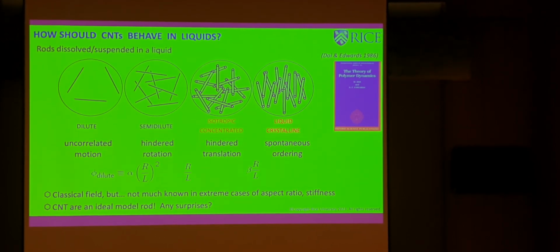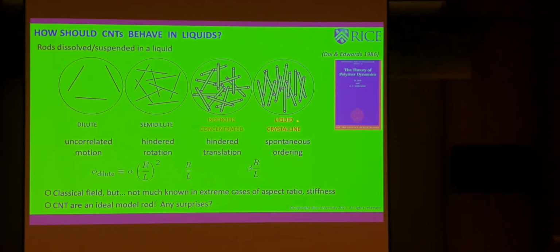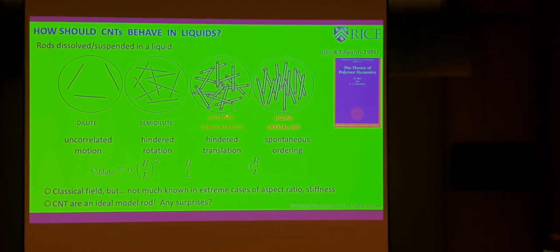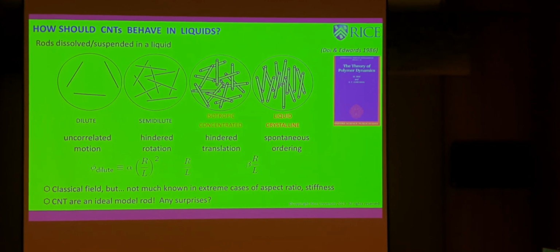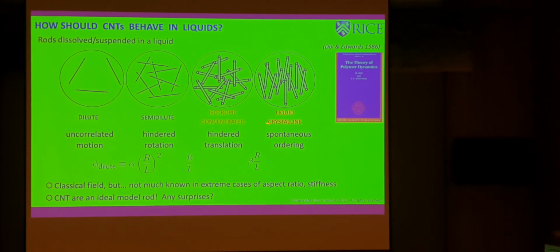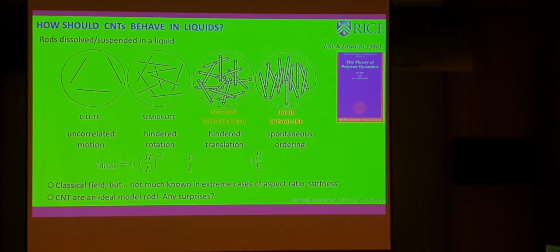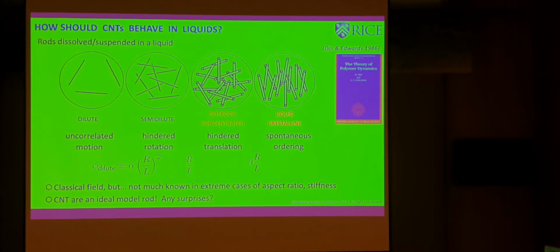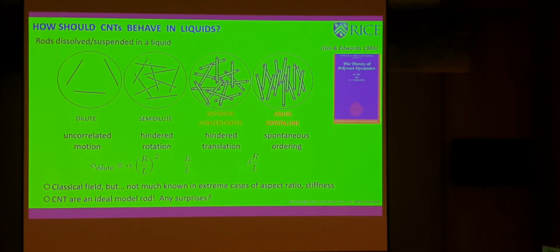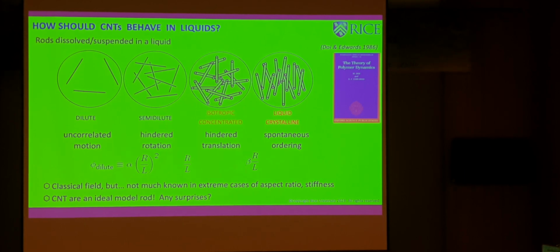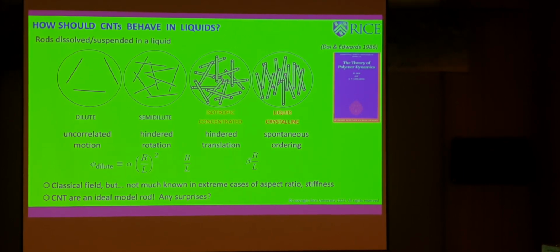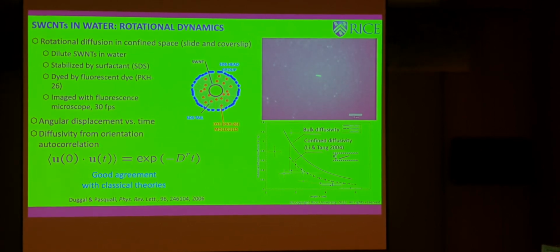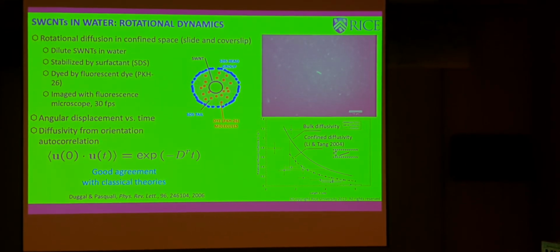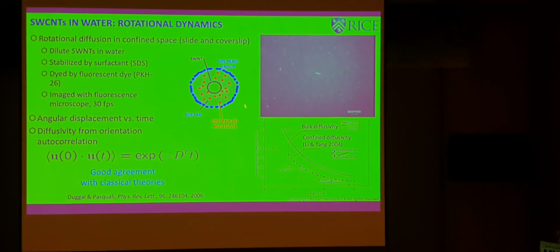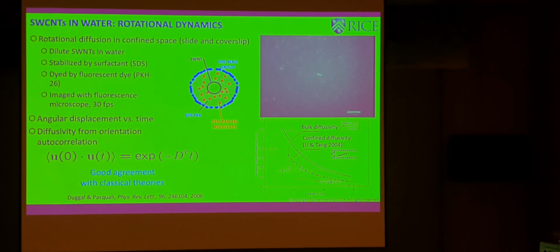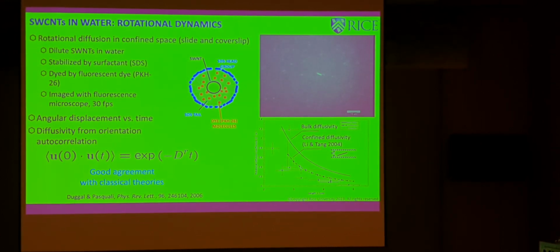And what's very important, this is already known for a century, is that when this type of liquid crystal appears, there is a region of phase space, or a range of concentrations, where these two phases are in equilibrium with each other. So you have an isotropic phase and a liquid crystalline phase in equilibrium, and then you can go to higher concentration. So we set out to see whether it was working. Now, this is before the 2013 paper, right, to get the basic science. And indeed, if you look at individualized carbon nanotubes in water, you see they behave a lot like rods. In fact, you can use the equations for rods and confined rods to actually model their diffusivity.